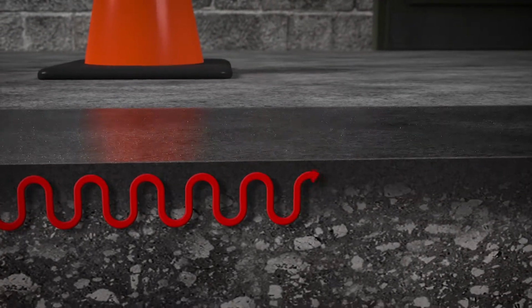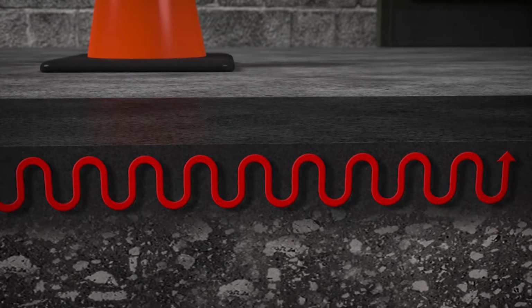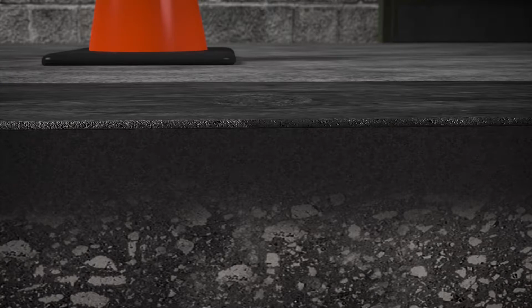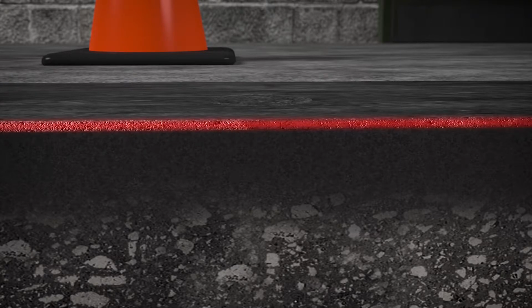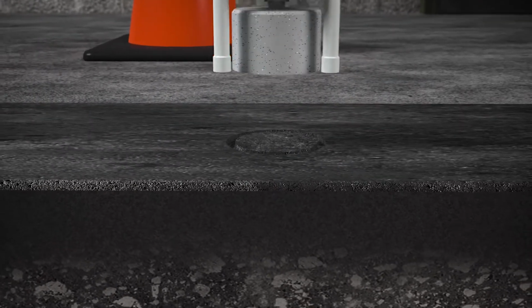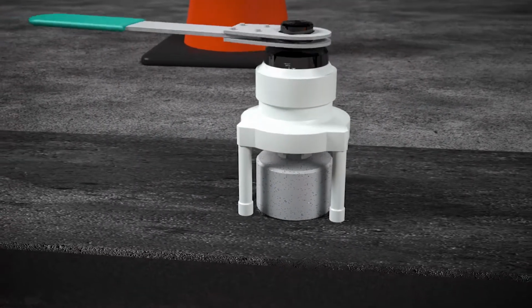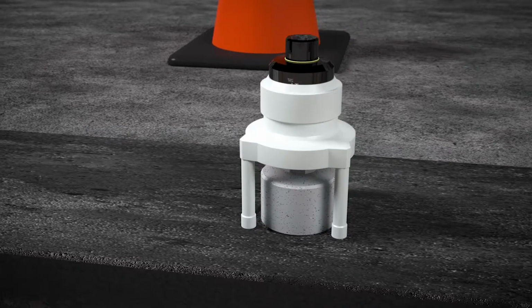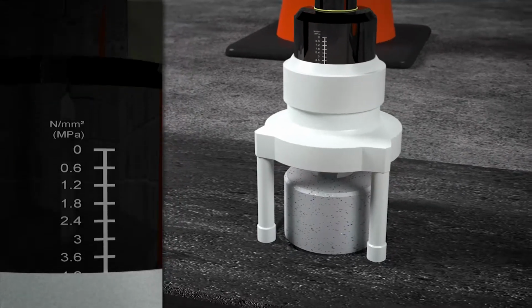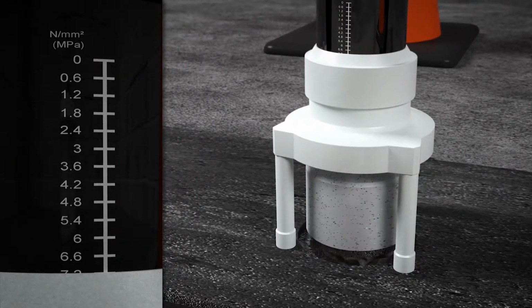So that's going to come into its own when we're applying subsequent coatings whilst the activator is still wet. What this means in practice is we're achieving a chemical bond in addition to a mechanical bond. This allows us to achieve bond strengths of anywhere between 6 to 7 megapascals. Most other products on the market achieve between sort of 2.5 to 3.5. The activator is allowing the coating and the concrete to act monolithically. It's going to act as one. It's a complete bulletproof system.